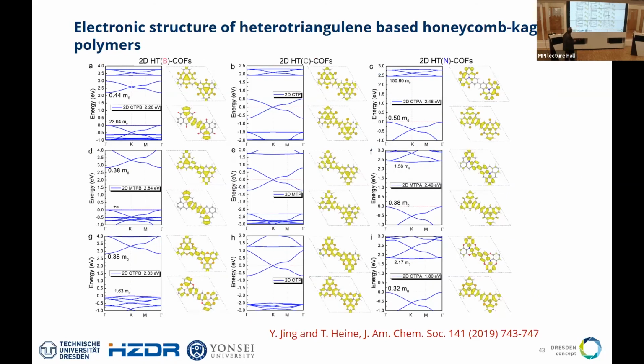So that was quite interesting. We looked into that, and if you put in the atomistic realization, you really see what we were predicting in this very first, very simple picture. Okay, just here for some examples to convince you. In this particular COF, we have an effective mass of the electrons of 0.44, and 23 for these very heavy holes. Right here, for the carbon system, the Dirac point is always directly at the Fermi level. And here for the nitrogen ones, you would have electrons of 150 electron masses, but half an electron mass for the holes. So that's, wow, interesting. You can tune your semiconductor, you can make very polar semiconductors that conduct either only electrons or only holes.